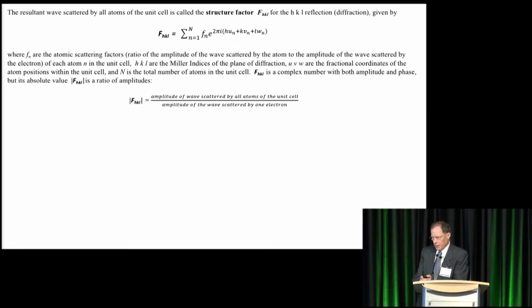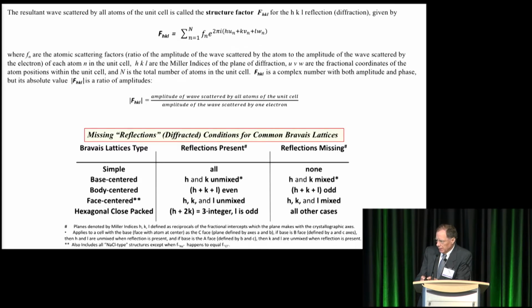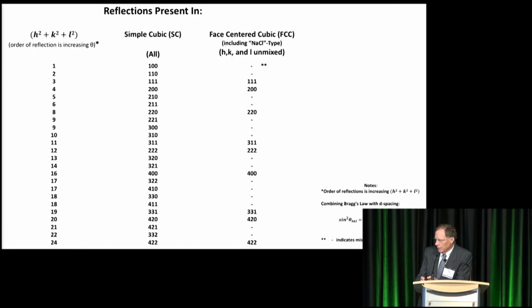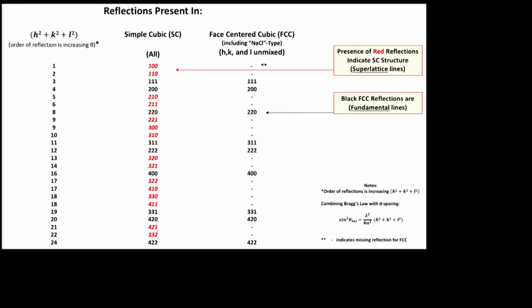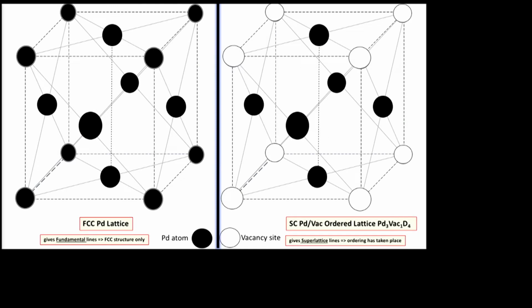I'm also going to have to break my heart here and skip this because I was so interested in your understanding the background of why the X-ray diffraction superlattice reflections do solidly confirm the presence of the simple cubic structure, which is the superabundant vacancy form. But basically, the red reflections prove that it's simple cubic rather than face-centered cubic, where there are only the basic fundamental reflections. And the structure that we're talking about is shown on the right here.